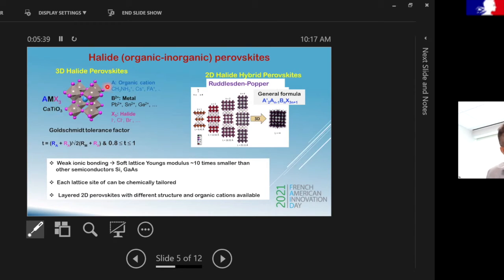And so what happened is that people were able to make a hybrid version or a halide version of this, where they were able to replace this A, which was calcium, with an organic cation or even an inorganic like a cesium or a combination of these three. The M, the metal here, the titanium, was replaced by a divalent metal, which is lead 2+ or tin or germanium, and there could be other options as well. And the oxygen was replaced by a halide, either iodine, chlorine, or bromine.